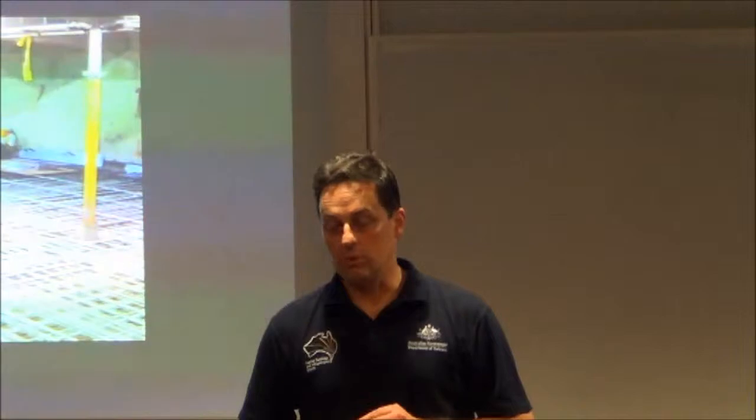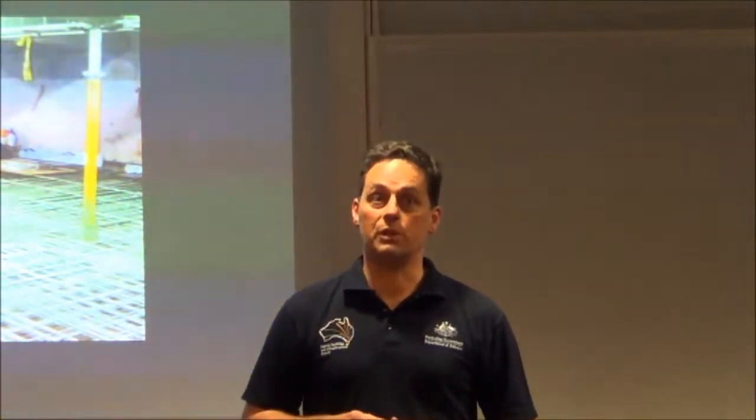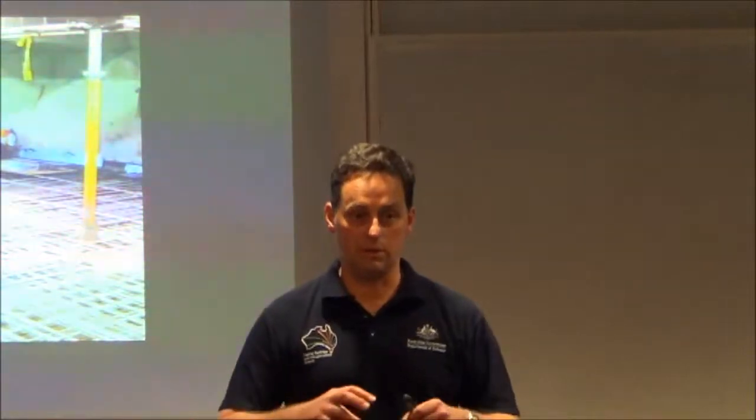So how are the lap lengths compared to steel? About the same. And is there any other connection methods? No, really not. So there probably could be. You could probably bolt or use a form of double-ended bolt. I think there was a magnesium bolt or something like that. It was a very high-priced metal that they were looking at to do the tensile coupling of two bars. But really, the best thing to do is probably use a decent splice length. About 40D, I think. I think steel's 40D from memory. It'll be about that. So if you're looking at a 16mm bar, you're probably looking at about 600mm to splice between the two.